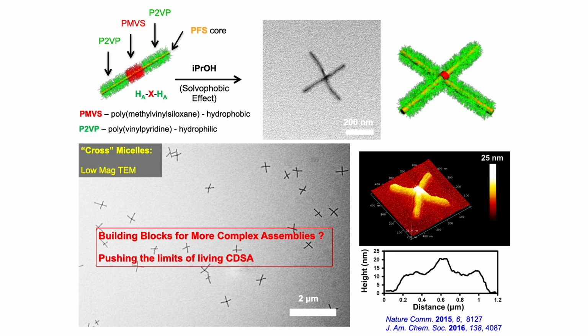Here's a micrograph of these cross structures, and the two fiber-like micelles lay over the top of one another. This is called a height image by atomic force microscopy. Here's the height trace, you can see where they cross over is much higher because they're crossed over like this.